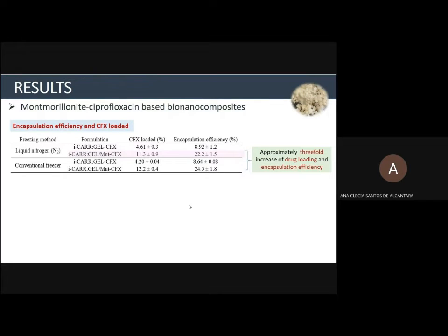Once the montmorillonite-ciprofloxacin hybrid material was characterized, this intercalation compound is added to the biopolymer matrix, and the porous beads are prepared by two different methods, by liquid nitrogen or conventional freezing. The encapsulation efficiency and the loading of the drug in these systems were also evaluated. It was observed approximately three times more drug loading and encapsulation efficiency in the materials based on the intercalation compound compared to the analogous materials prepared with free ciprofloxacin